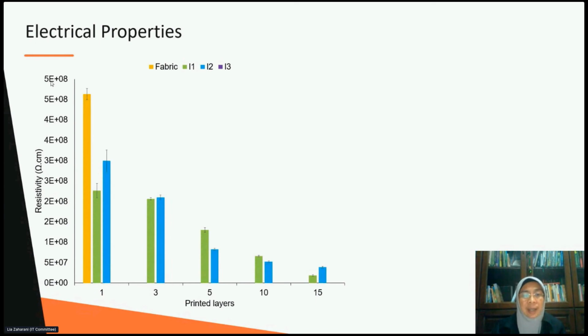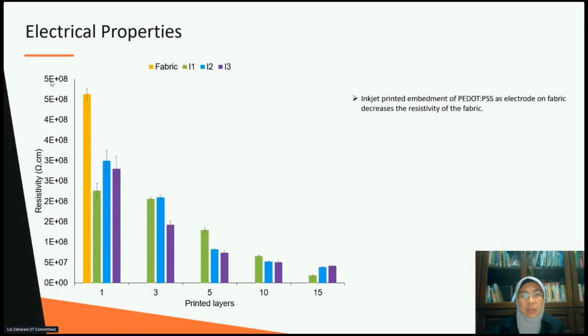So basically this is all the results obtained. Ink 1 is green in color, blue is for ink 2, and purple is for ink 3. We can see that at 15 layers, the resistivity of ink 2 and ink 3 increases in comparison with ink 1 because of the limits of charge carrier mobility between the dried particles in an inkjet printed film, caused by the interactions between the PEDOT:PSS, silver nanoparticles, and co-solvent.